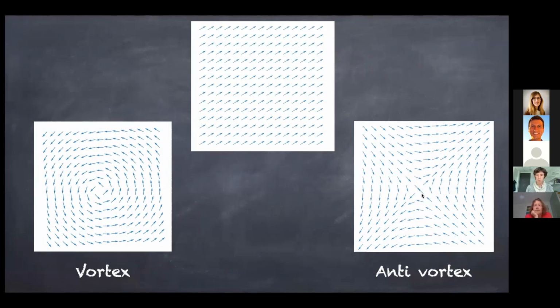Same thing here, but with a winding number of -1 instead. So these are local minima of the Hamiltonian. Now, on a finite lattice, obviously any configuration has finite energy. But as the lattice size gets larger and larger, it turns out that even though these spins are closely aligned, if you let the lattice size go to infinity, all those not quite perfectly aligned contributions to the energy add up to infinity. So the total energy diverges for a single vortex, and same thing for a single anti-vortex.